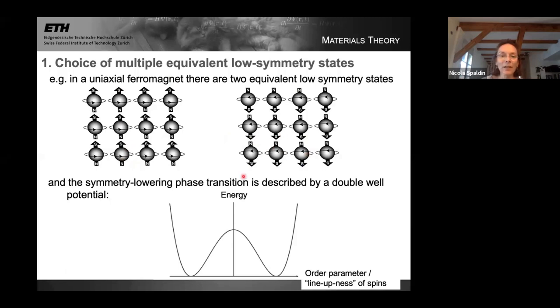So we often then would describe the phase transition in terms of its potential energy surface. And in this case, the energy, as a function of some order parameter, which is kind of how much the spins are lined up, is a double well. It's a maximum when the spins are not lined up at all. That's the paramagnetic state. And it lowers its energy to a minimum, either for all the spins pointing down or an opposite minimum for all the spins pointing up. Okay, so this is the second feature. I called the symmetry lowering feature number one because it was kind of obvious. The next feature is that there is a choice of multiple equivalent low symmetry states.